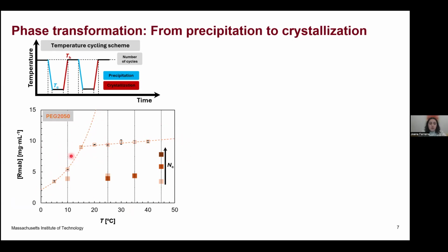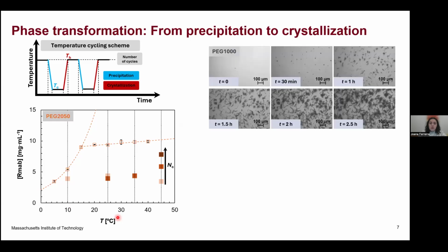So at a high temperature, mostly the formation of crystals, while at a lower temperature, mostly precipitation. So that's the reason you have here a significant drop in the concentration as a function of temperature. We also did some time-lapse experiments. In this case, we mostly observed crystals, and it was also nice that over time we could estimate some kinetics and observe the nice growth, the length increase of the crystals over time.